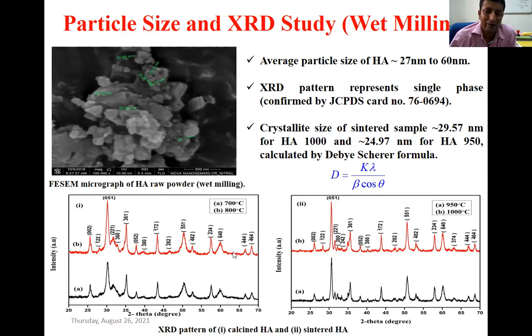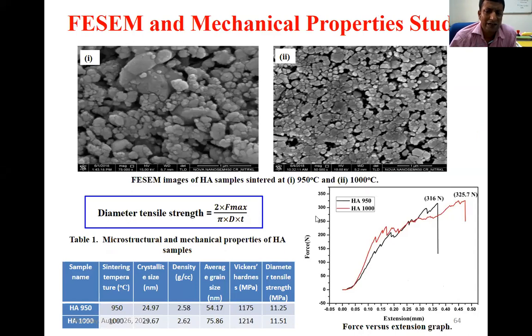We did sintering at 950 and 1000 degrees Celsius, and at 1000 degrees Celsius we are getting better properties, whereas by the conventional method the optimized sintering temperature is 1300. So this is a very drastic decrease in temperature and time, here also 15 minutes. Ordinarily we use chemical processes to obtain nanoparticles, but that is only for research purposes. Via this technique we can go for industry, large scale production, because this is cost effective. During sintering at 950 and 1000 degrees, since we used the microwave, the particles remain in the nano stage, that is what we have seen.